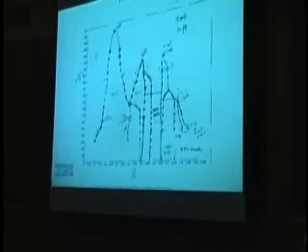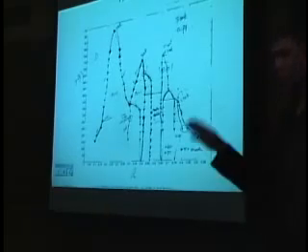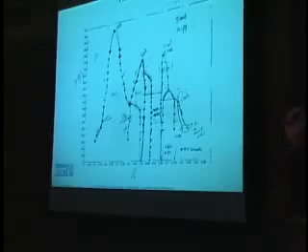That's people's first intuition: I'm going to actually look at the configuration in my system. Anytime systems are partially disordered, just looking at them is the best way to fool you. If you look at something partially disordered, half of the class will say it's ordered and half of the class will say it's disordered. It's really the thermodynamic behavior that tells you in which phase it still is. If it's in an ordered state, a compound state, that means you should be able to push it to a disordered state. That means you should see a phase transition somewhere as you raise the temperature or drive the chemical potential to another phase. If it's already disordered, if you heat it further, it won't go through a phase transition anymore.